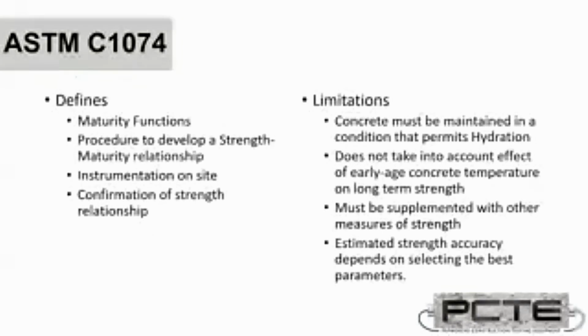So if someone says concrete maturity and they refer to ASTM C1074, it's a very precise definition. The standard defines two mathematical functions, which will give us our maturity index. It also defines the procedure to develop the strength maturity relationship. And that's a specific procedure. Sometimes people will work to different procedures, so they're going beyond the standard. They define the instrumentation to be used on site. And as Nat's mentioned, they actually have some information about confirming that the correlation built in the lab remains true.